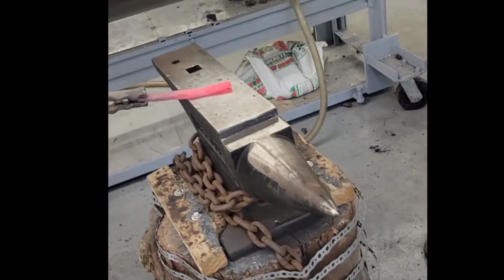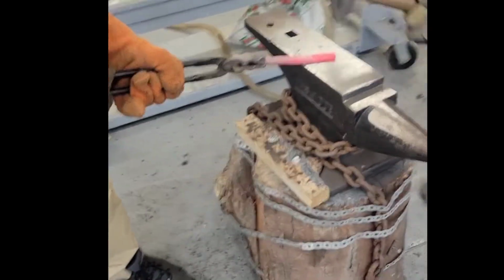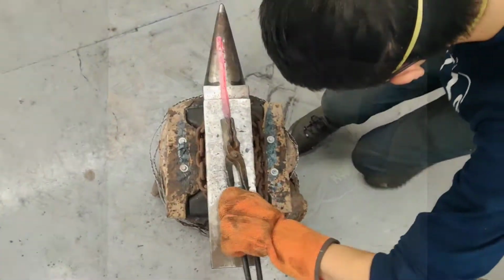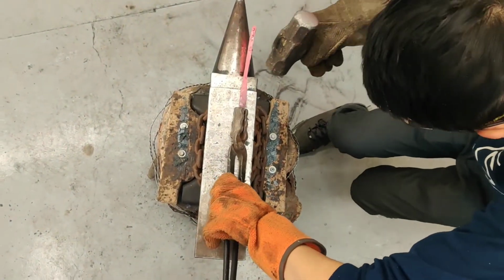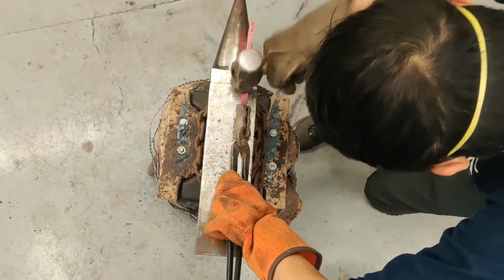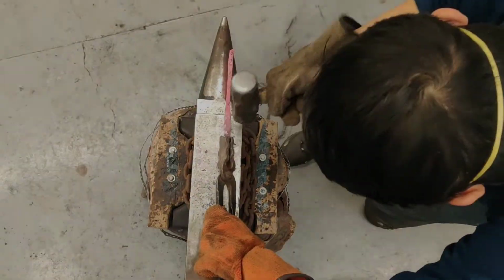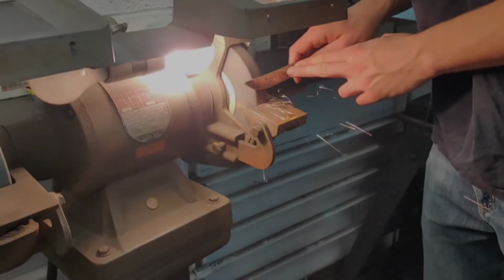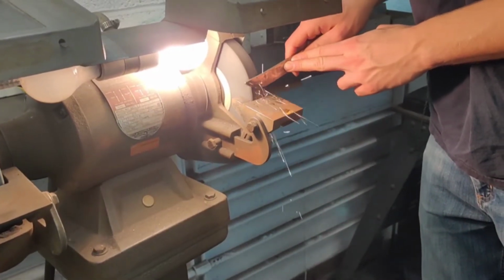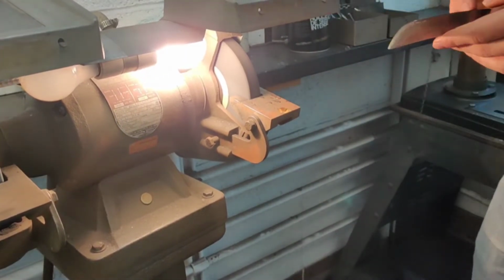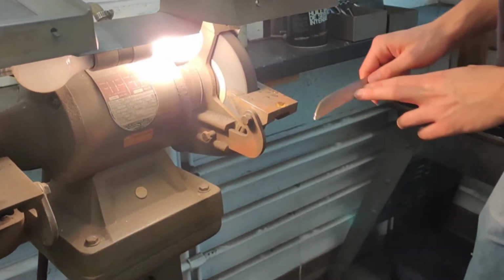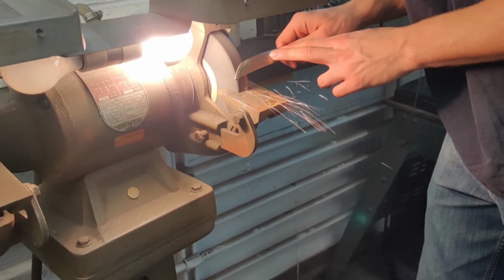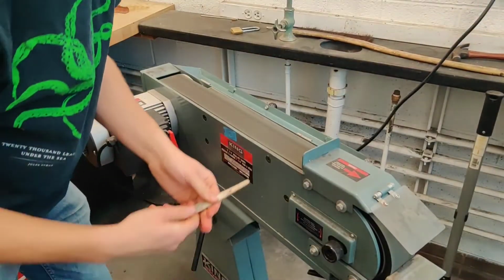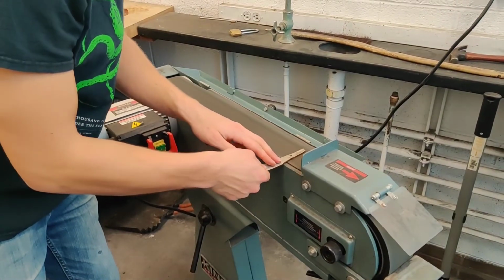By firing up our hand-built air coke furnace, the slab of material was placed inside and heated up to approximately 1100 degrees Celsius. Team members made sure to take great care around the furnace, not to come into contact with the hot metal and furnace bricks, following forge rules and wearing the necessary protective equipment including goggles, heat-resistant gloves, masks, and steel-toe boots. Unfortunately, not all blades are perfect, and the furnace became hot enough to melt the blade. After some tweaks to the design, the team kept going to get the most out of the material.